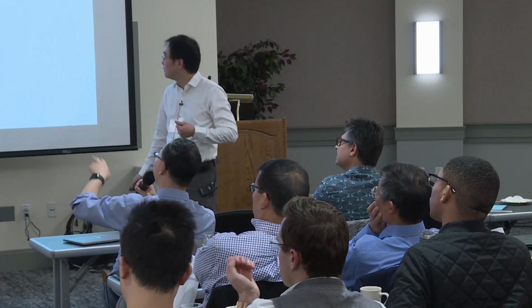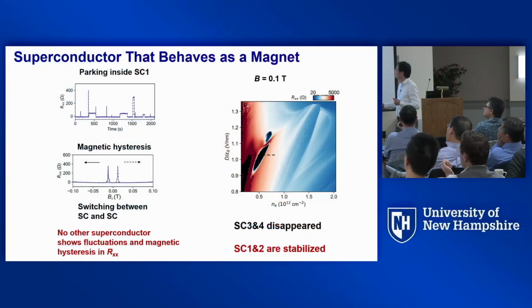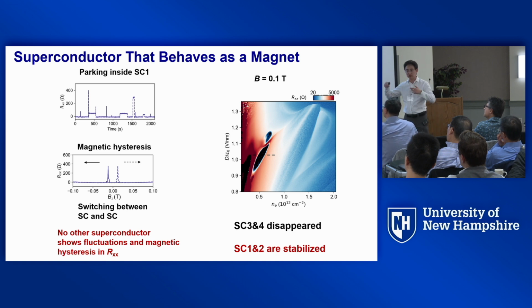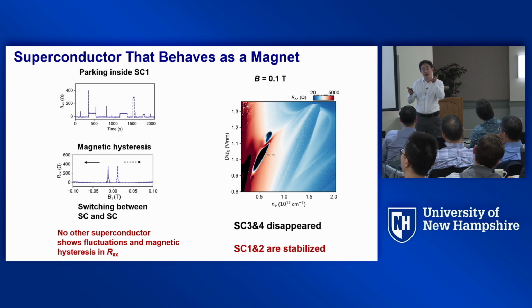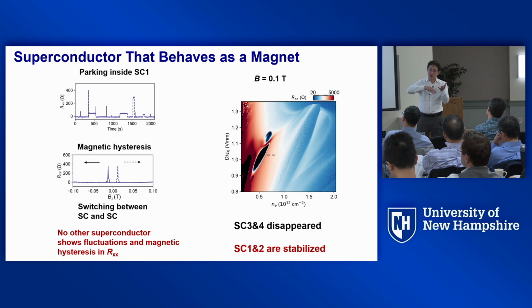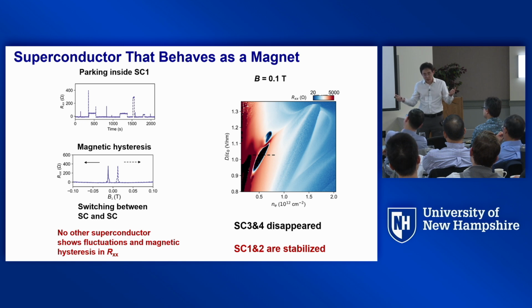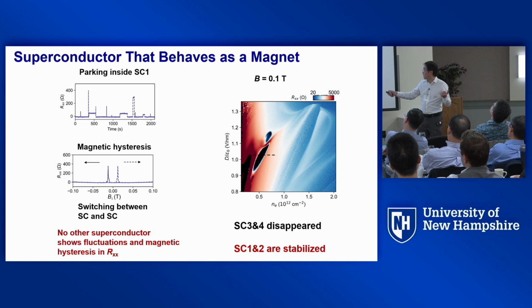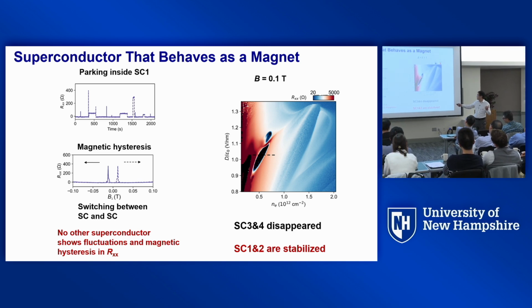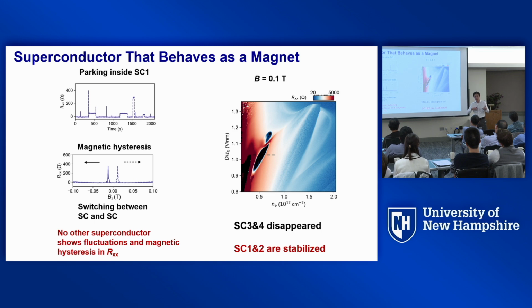So in your time fluctuation plot, there are also some plateau formations with finite resistivity? So I can tell you what we are thinking about this fluctuation or plateau or spikes. If you think the superconductivity could be in the K valley or K prime valley, then it's fine that you can have a domain wall in between. Maybe what the thermal activation does is to trigger some domain wall motion that makes the sample switch from being polarized in the K valley to K prime valley. And when you have a domain wall intercepting the path from source to drain electrode, that domain wall doesn't have to be zero resistance. And maybe that's what these spikes are. And we know experimentally the normal state of this superconductivity has a resistance on the order of 2 kilo-ohm, while all these spikes and fluctuations are much smaller than that. So it doesn't feel like the whole thing becomes non-superconducting.